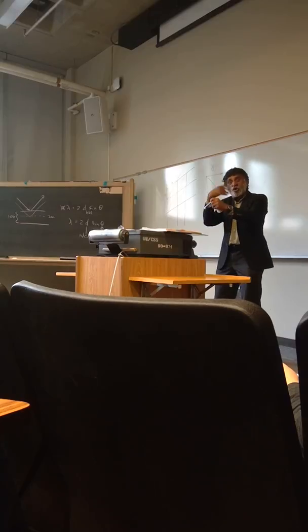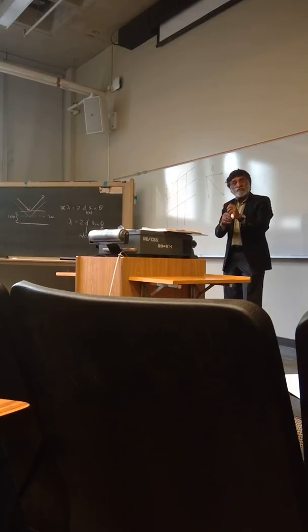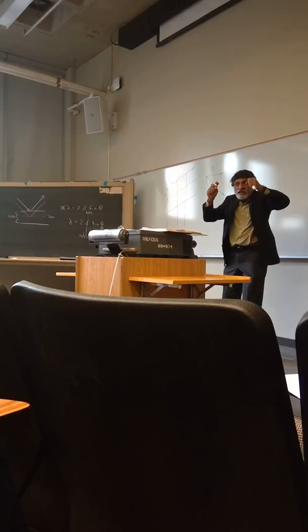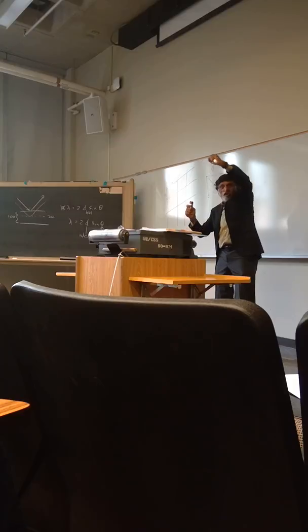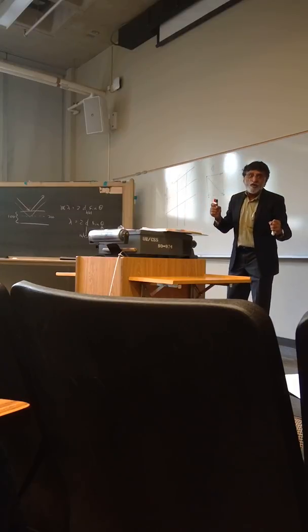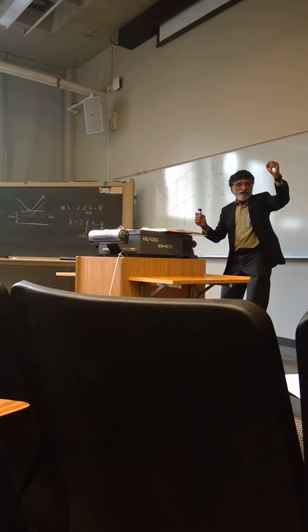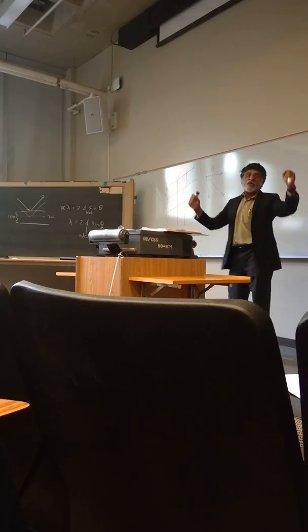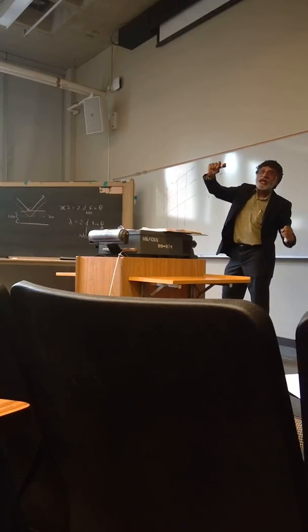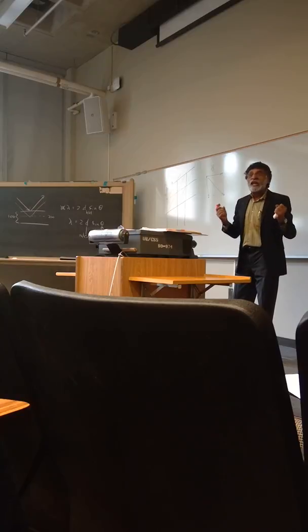So one way to look at the diffraction that you do in Bragg's law is that you keep the crystal the same, and then you rotate your incident beam. You can also do it the other way around. You can keep the beam the same, and rotate the crystal, and then as you rotate the crystal, you actually rotate the reciprocal lattice. And so you can formulate the whole diffraction law in terms of the reciprocal lattice.